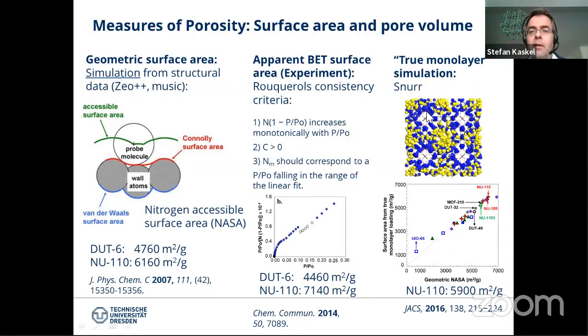However, these two models, the Snurr model and also here the simulation, nowadays we have computer programs like Zeo++ or MUSIC that can calculate geometric surface areas, they only relate to the crystal structure and they don't relate to an experiment which gives us information about the accessible surface area. Only the adsorption experiment gives us information about the accessible surface area or pore volume.